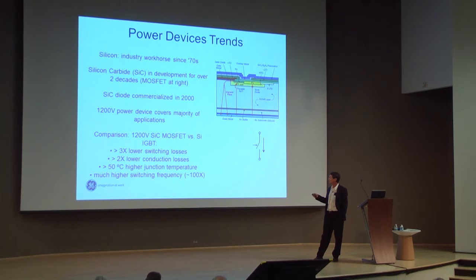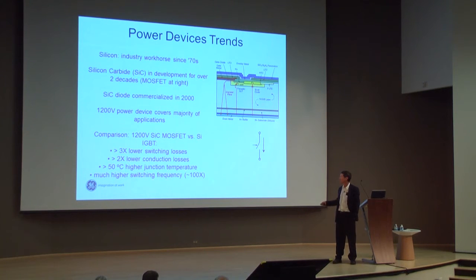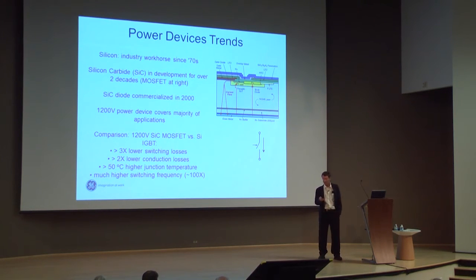You can look at the progress that's happened in this area. A lot of people are getting into the silicon carbide area. If you compare a 1200 volt silicon carbide MOSFET versus a silicon IGBT in the same range, you can get 3 times lower switching losses, 2 times lower conduction losses, and about 50 degrees higher operating temperature with the silicon carbide device, and all of that can give you a lot of benefit in the system. You can also get 100 times higher switching frequencies with silicon carbide devices. So we've been putting a lot of effort into this and are actually building a fab cooperatively in the state of New York right now for silicon carbide devices.